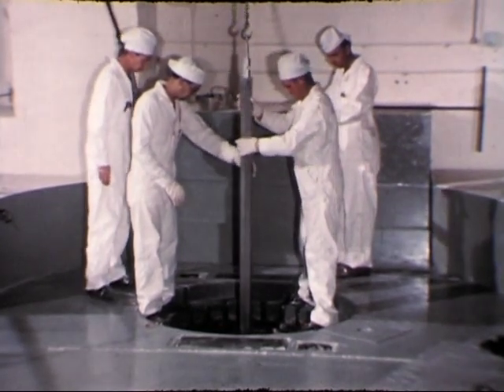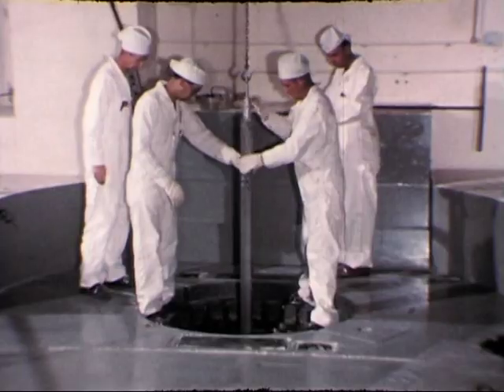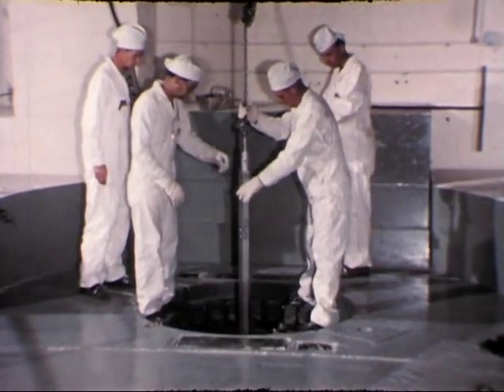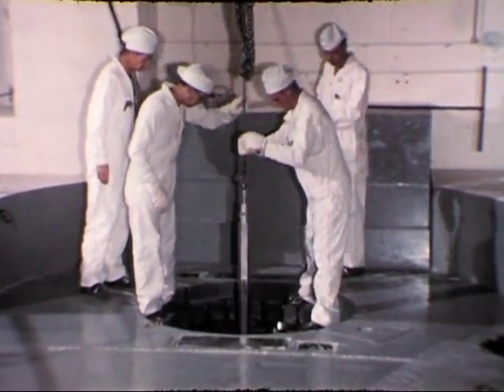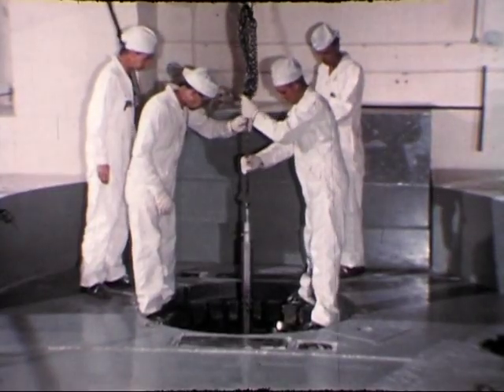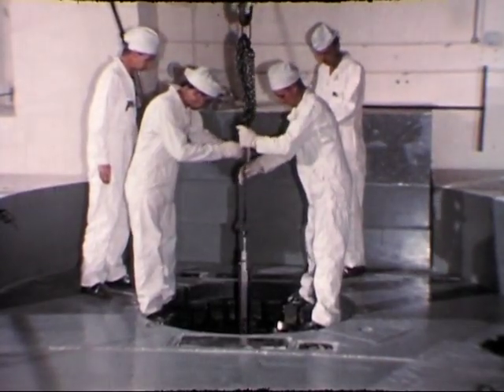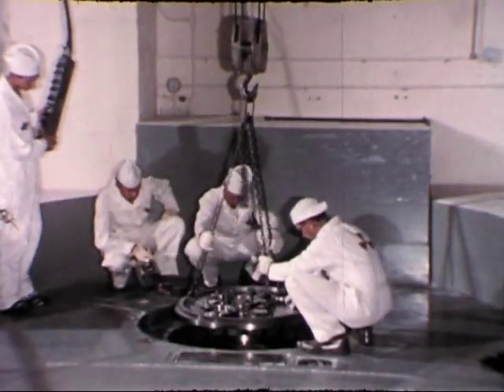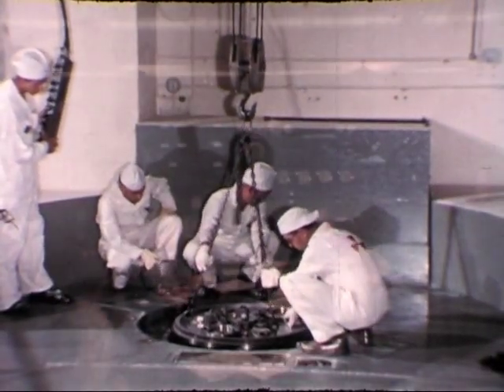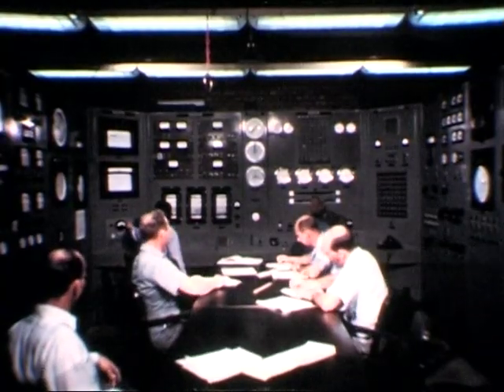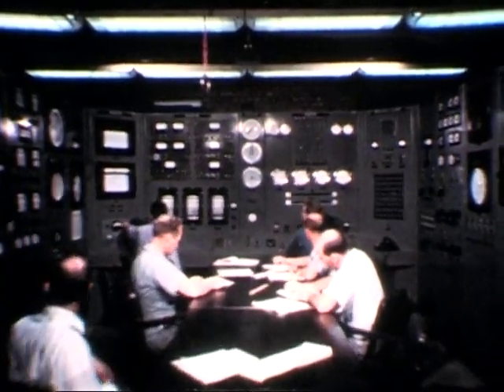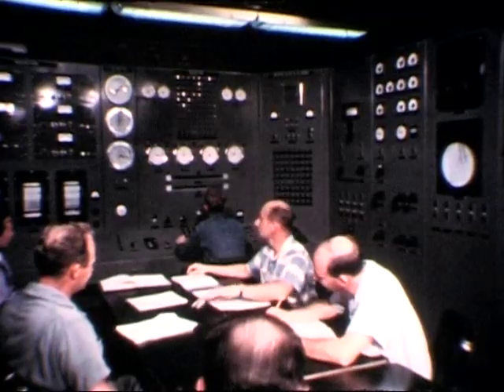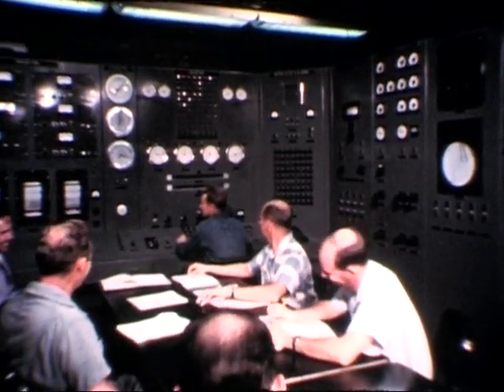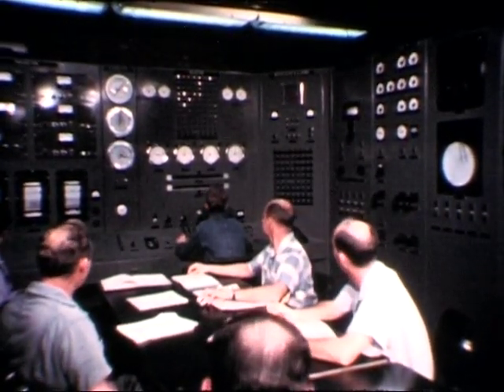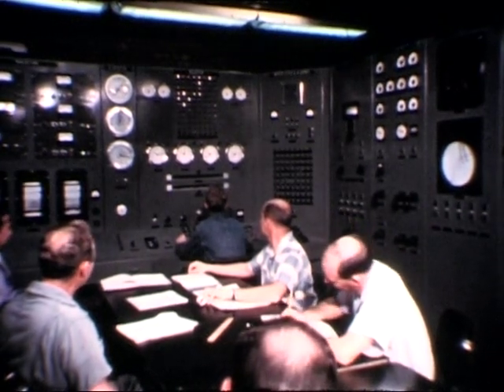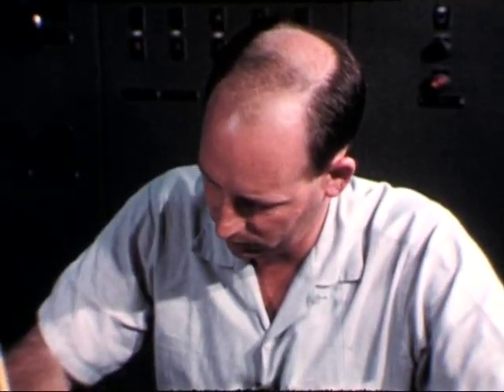The complete Mark III loading contains 19 subassemblies. 7 enriched subassemblies comprise the core. These are surrounded by a ring of 12 inner blanket subassemblies. Criticality was achieved on November 11, 1957. It was determined to be 47.4 kilograms of uranium-235, within 2% of the critical mass determined from the mock-up of the core on the Zero Power Reactor 3.